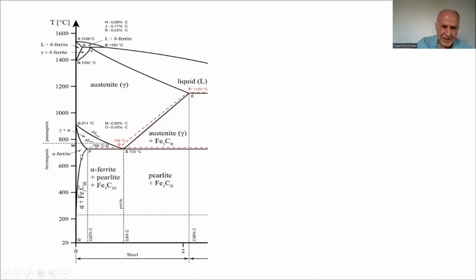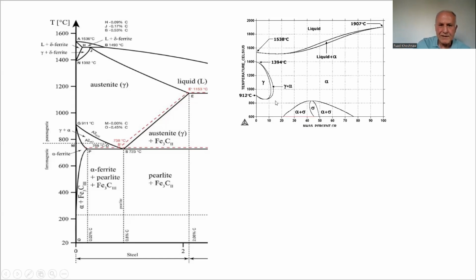So let's imagine this loop of alpha ferrite. If we add chromium, that makes this gamma loop smaller. So this gamma loop has become much smaller, and this one has become very large. This small triangle, let's say, has covered everything at room temperature, alpha. And this is with 10, 20, 30 chromium. From 20,